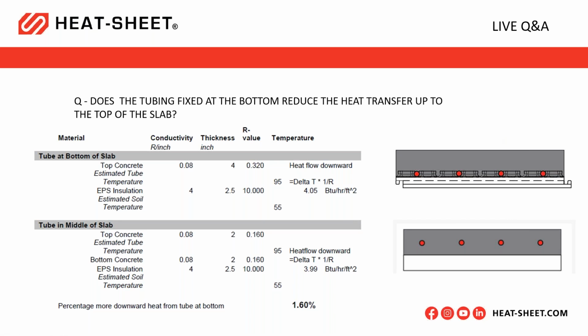Sure. We did get this question come up quite a few times. So we had some heat loss calculations done independently by a well-known building scientist. What he's showing is that for a 4-inch slab, when you have the PEX tubing at the middle of the slab versus the bottom of the slab, you increase the heat loss to the ground by 1.6%. So you get only 1.6% more heat loss with PEX tubing at the bottom of the slab versus the middle, which isn't a significant amount.